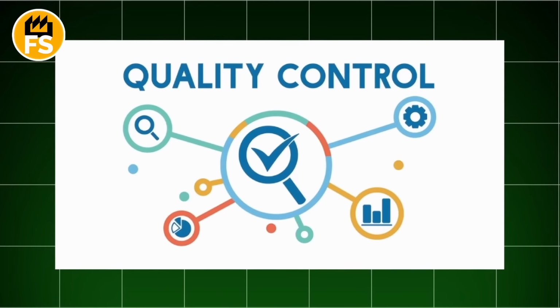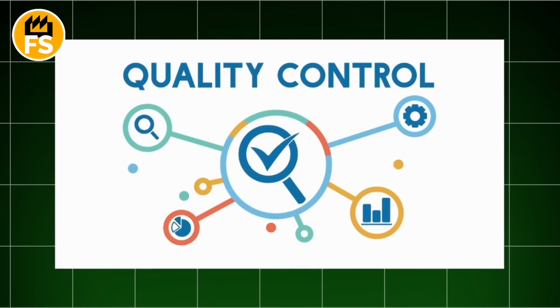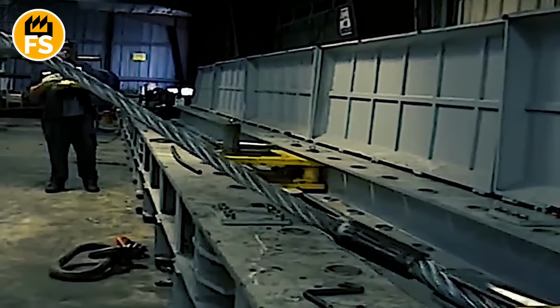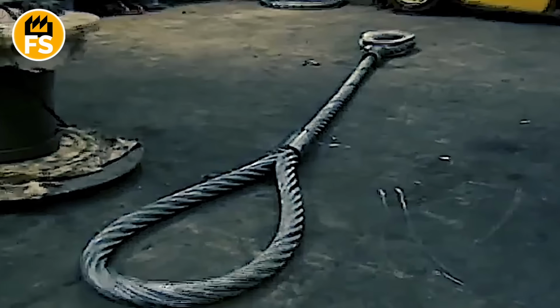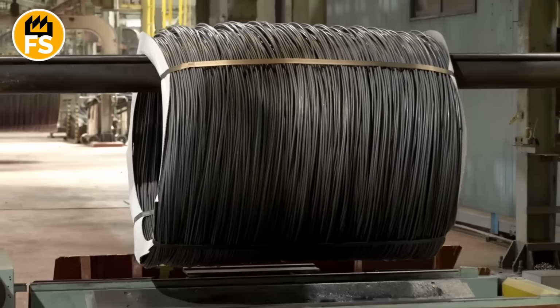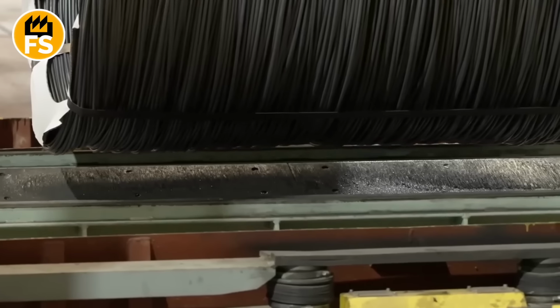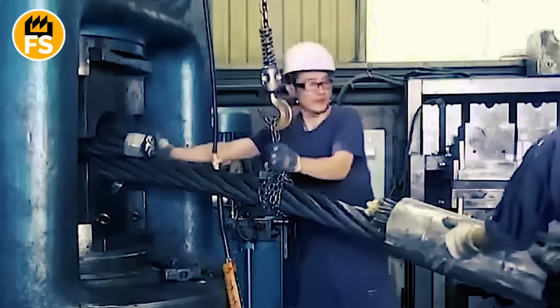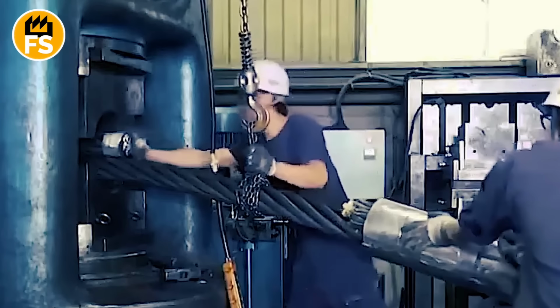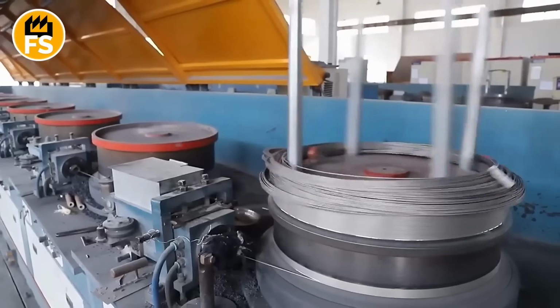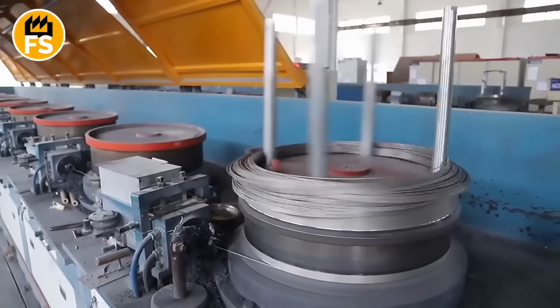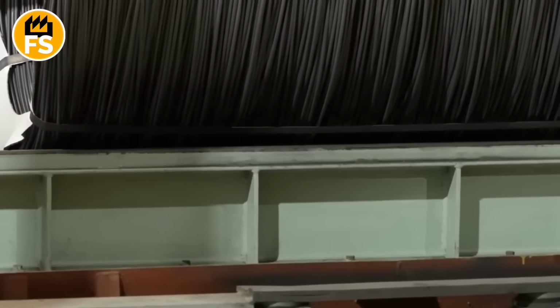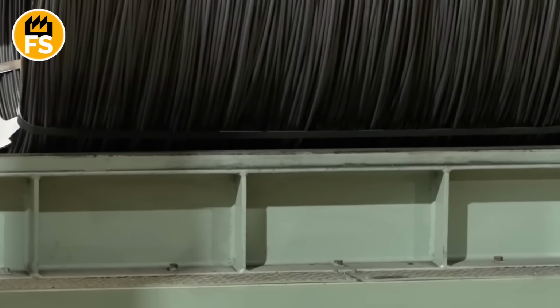In the final stage, the wire undergoes a final quality control, and this is definitely not a simple visual check. A long, almost continuous strand of shiny metal moves at a speed of tens of feet per second through the inspection unit. There, it's met by special sensors. This could be laser equipment that non-contact measures the wire's diameter with an accuracy of thousandths of an inch. Nearby, devices that determine strength.